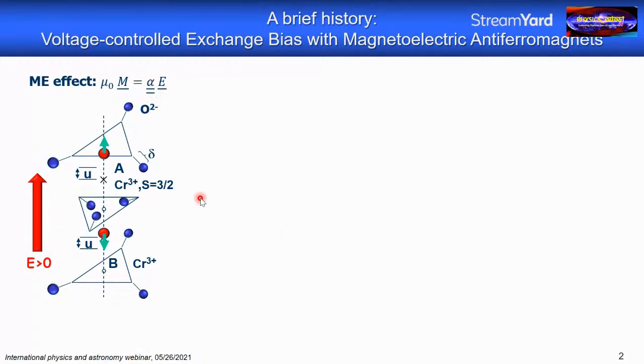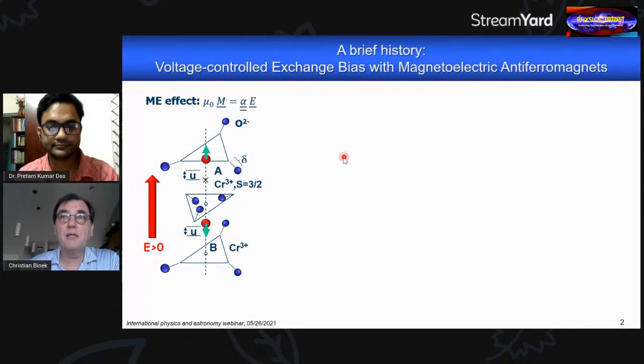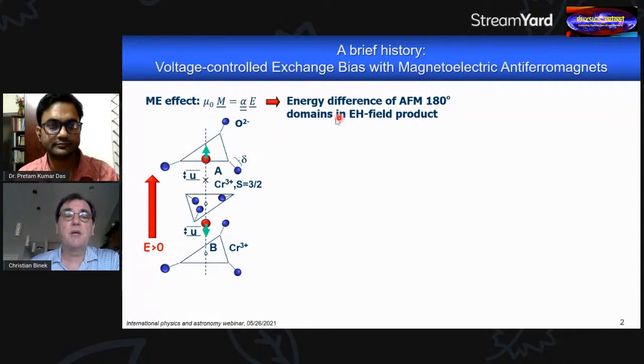So that is the linear magnetoelectric effect in this material, which happens once the system is magnetically ordered such that time inversion and spatial inversion symmetry are both broken, and their combined application is a symmetry operation of the system. Now, for our switching experiments, what is interesting is what happens when you apply an additional magnetic field. And if you apply an additional magnetic field, this magnetization, which we can induce by an electric field, experiences Zeeman energy, and that Zeeman energy depends on the orientation of the magnetization relative to the applied magnetic field.